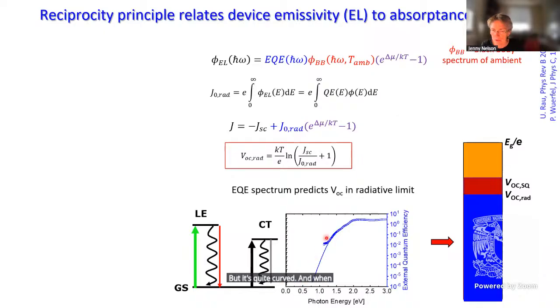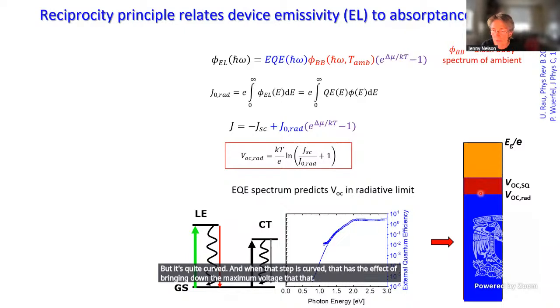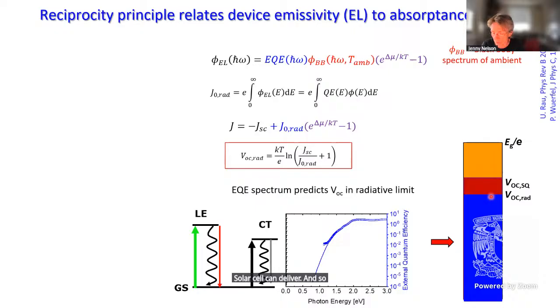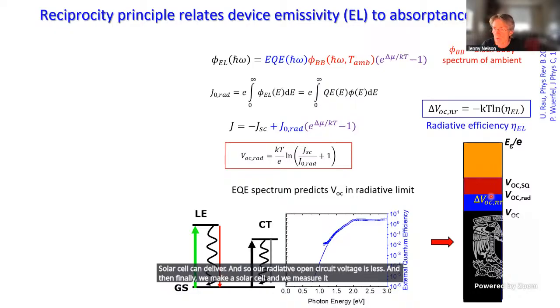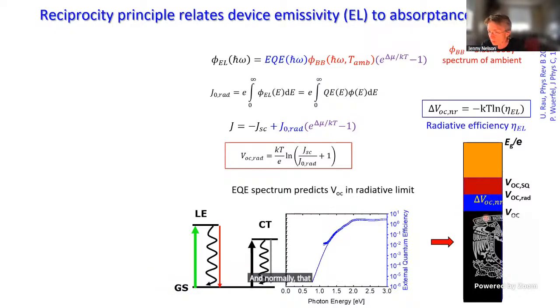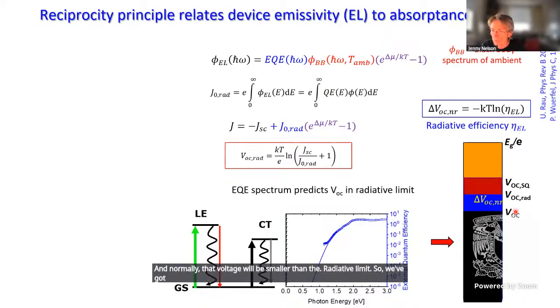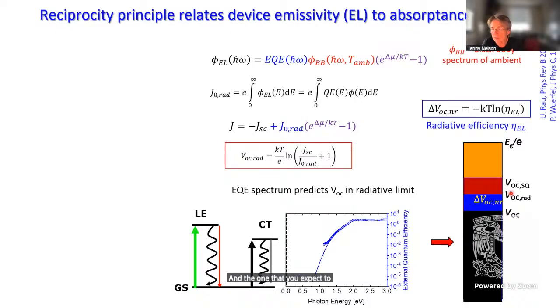And when that step is curved, that has the effect of bringing down the maximum voltage that solar cell can deliver. And so our radiative open circuit voltage is less. And then finally, we make a solar cell and we measure it and we see what voltage we get. And normally that voltage will be smaller than the radiative limit. So we've got now a gap between the real voltage that you measure from the solar cell and the one that you expect to have from that solar cell if the material with this EQE spectrum was working in the radiative limit. And the difference between these can be quantified in two different ways.